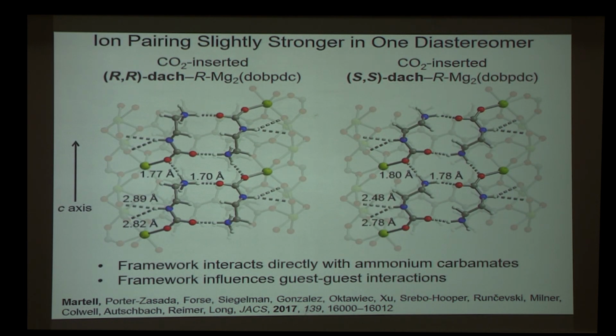This is now a different view of that structure. Here are the ion pairing interactions in the long chains. Here is the ion pairing between chains of ammonium carbamate. And both diastereomers show these key ion pairing interactions, but you can see in this diastereomer, the distances are substantially shorter, suggesting that this diastereomer should be more stable, and that is indeed consistent with the CO2 capture results.